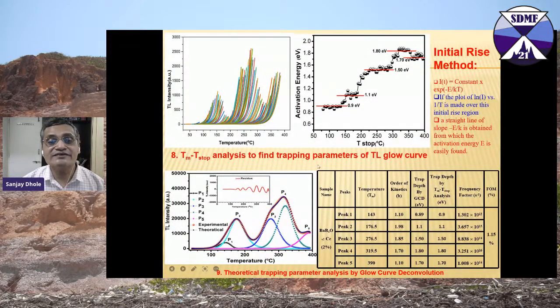The analysis finds the trapping parameters of the TL glow curve. TM-TStop is basically a very important technique where you can calculate the energy of the trapping levels. So there are 0.9 electron volt, 1.1 electron volt, 1.5 electron volt, 1.7, which is comparable with the theoretical one. This is the trap depth which has been calculated by GCD. This is Chen's formula, and this is quite comparable.